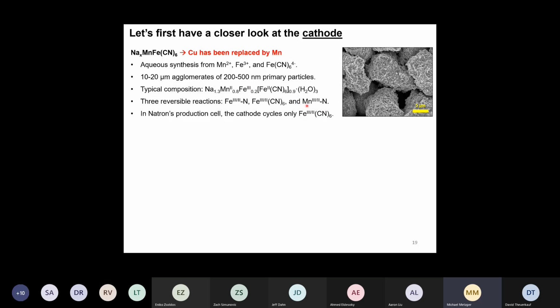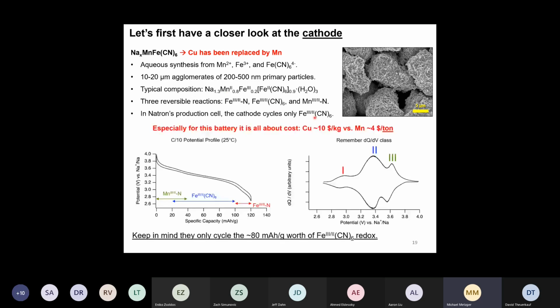Or another option for charge compensation in these materials is that the manganese that is now there instead of the copper can change its oxidation state between 2+ and 3+, and this manganese is also coordinated to nitrogen, same as this iron. And Natron, though, doesn't make use of all these different redox couples that are available in the cell. They limit themselves to the Fe 2+, 3+ redox, and they use the Fe atom that is coordinated to the carbon.